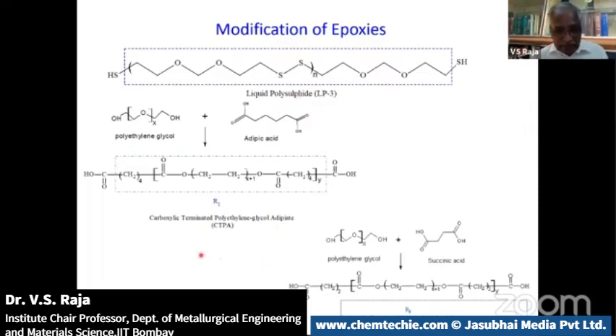Can we incorporate carboxylic terminated polyethylene glycol adipate? We synthesize this particular CTPA. We synthesize again carboxylic terminated polyethylene glycol succinate. We synthesize these compounds and then we cross-link them along with the normal epoxy. What is the advantage? These are linear chains. They are almost aliphatic now. So you have a combination which is aliphatic, having good resilience, whereas aromatic gives much more cross-linking and brittle structures. So you can put them together, then the molecule will have better toughness.